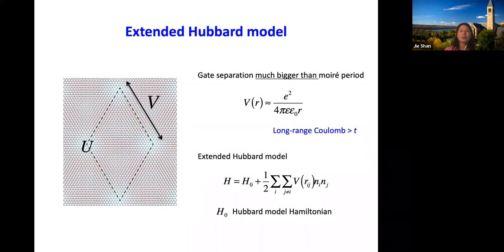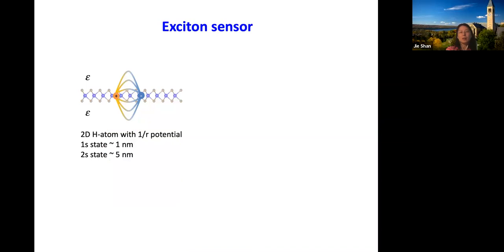So the question is, how do we come up with a better, more sensitive way to probe those states? This is the approach we have tried. It utilizes a property of excitons in a monolayer semiconductor. I've already mentioned that exciton interaction is very strong in this material. They form bound states and look like a two-dimensional hydrogen atom with a 1/r potential. So they have a series of Rydberg states, 1s, 2s, and so on. The 1s is strongly bound, with a Bohr radius on the order of a nanometer, the 2s is on the order of 5 nanometers, and the 3s would be bigger.